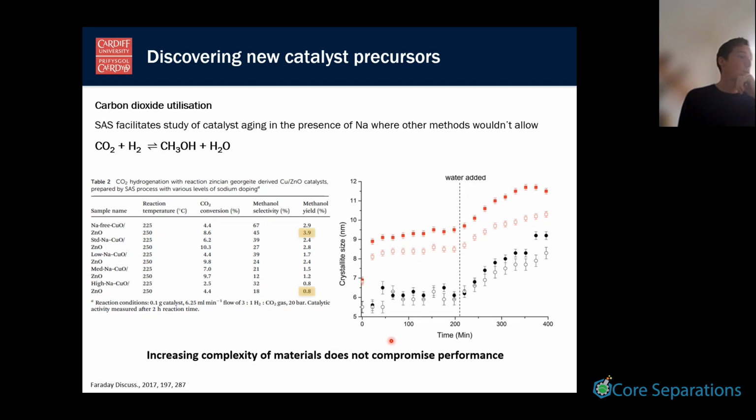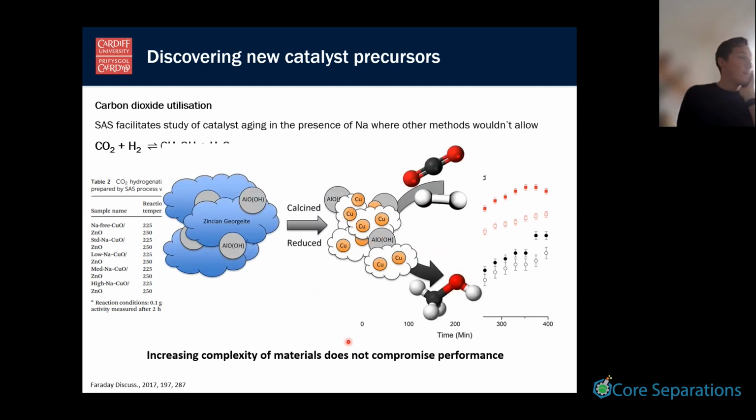And using an in situ XRD experiment, we can track the formation of copper crystallites. In the presence of water and sodium, you find that the copper crystallite size increases very rapidly compared to the sodium-free one, which is this line here. I won't talk about this in too much detail as I don't have time, but I want to make the point that the complexity of these materials is also not a barrier.